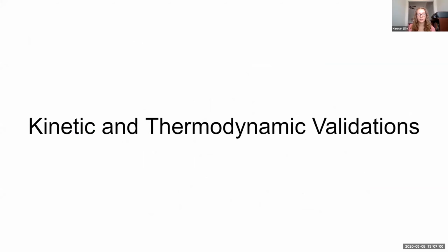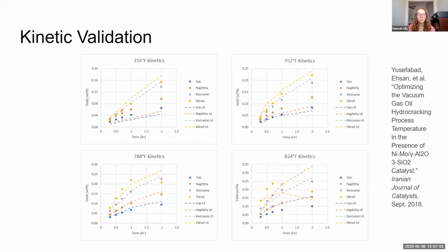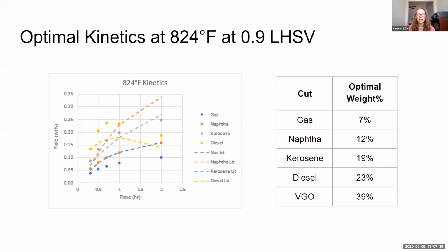Now we're going to take a look at our kinetic and our thermodynamic validations. To validate our kinetics, we used a literature source that cracked VGO into 4 components, which were diesel, kerosene, naphtha, and gas, like Mitchell mentioned earlier. So we validated these kinetics at the 4 temperatures in these graphs below. It's important to note that in the literature, the reactor was held at a pressure of 2200 PSI, so we also applied this to our reactor. After reactor optimization, we determined that the optimal temperature and residence time for our kinetics were 824 degrees Fahrenheit and an LHSV of 0.9 hours, which is about 55 minutes.